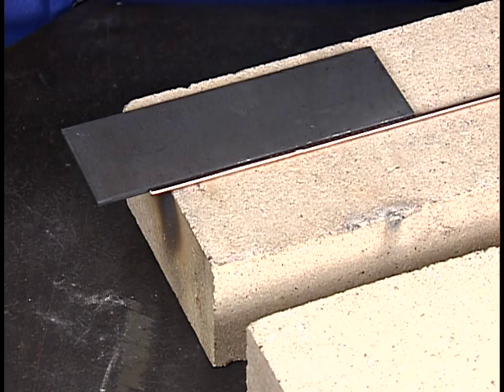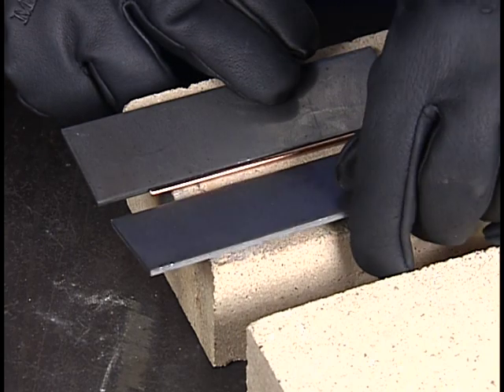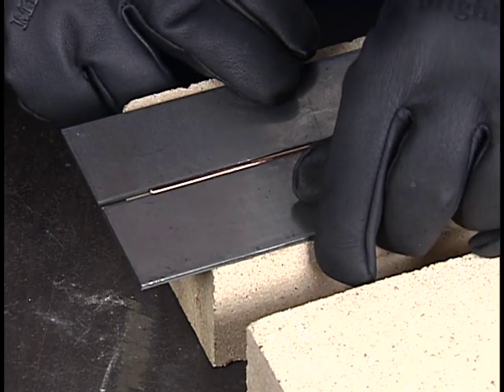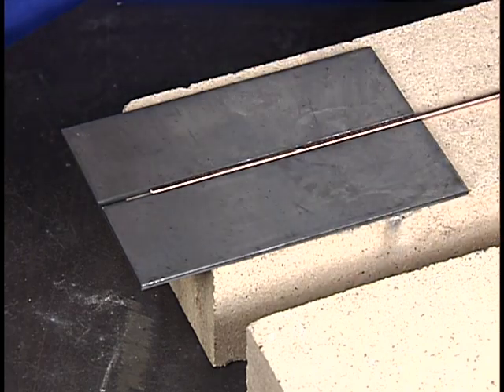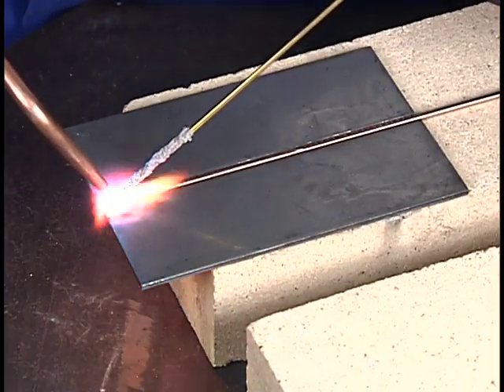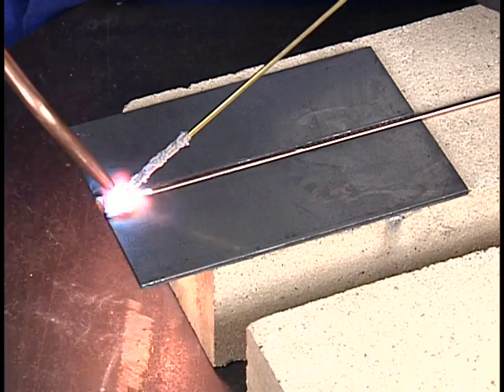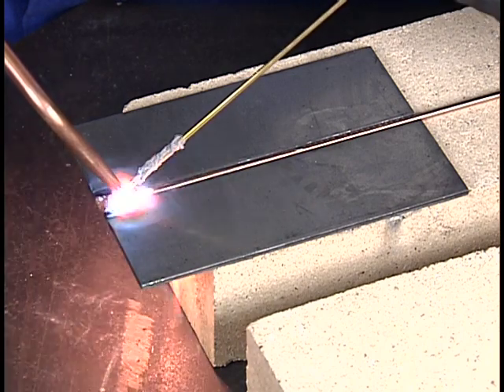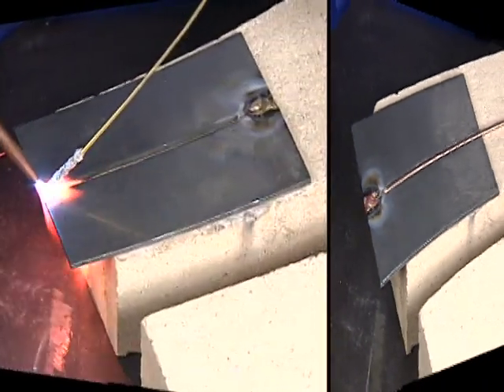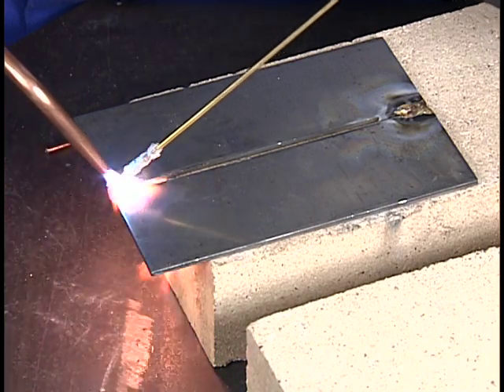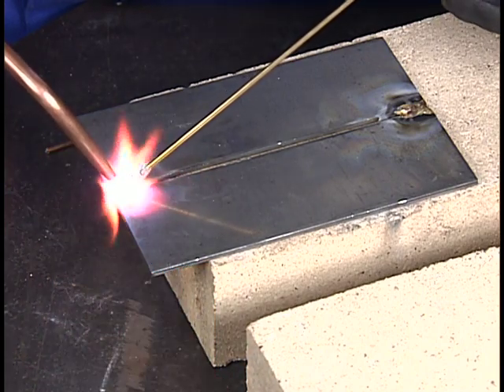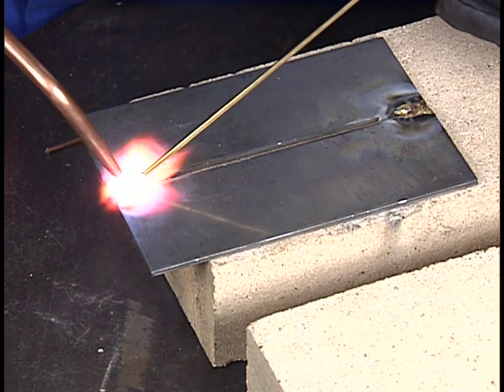Place 2 plates together to form a butt joint and use a 1/8 inch spacer between the plates to make a 1/8 inch root opening. Deposit a 1/4 inch tack weld using filler metal at one end of the plates. Adjust the opening as needed, then deposit a second 1/4 inch tack weld on the other end of the plates.